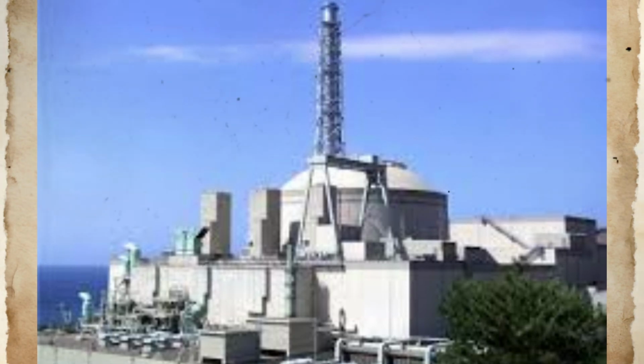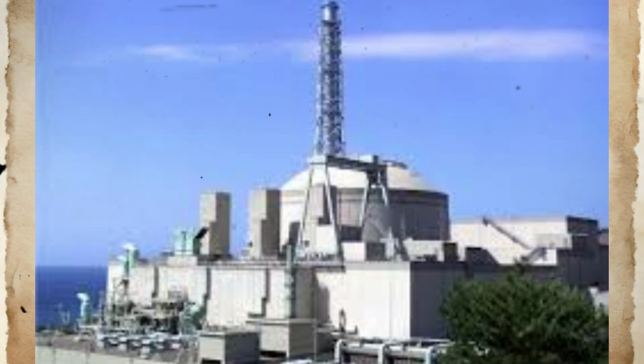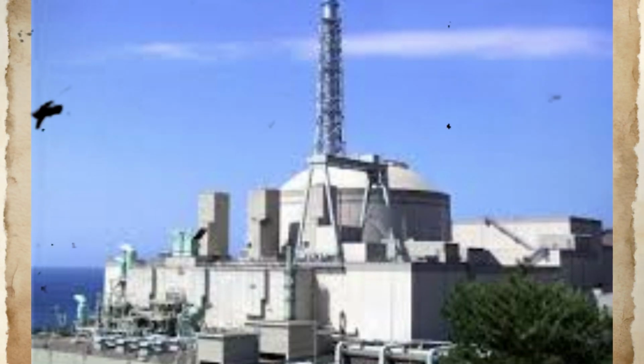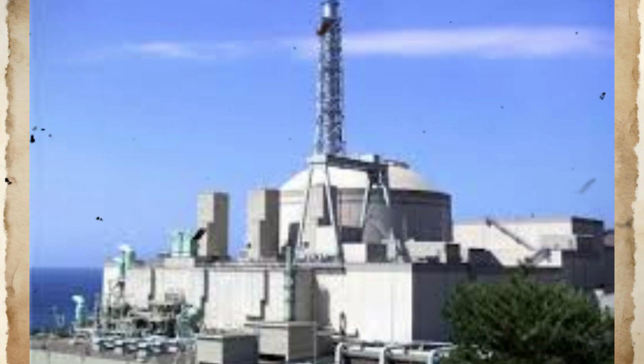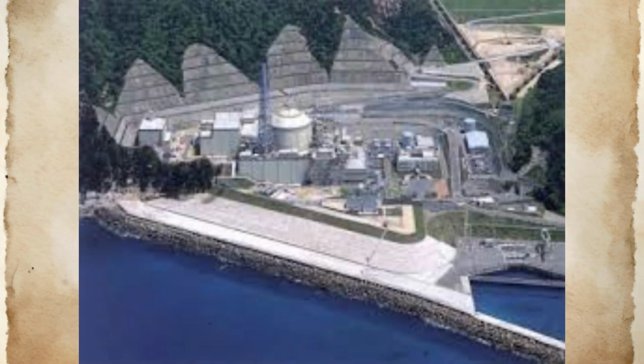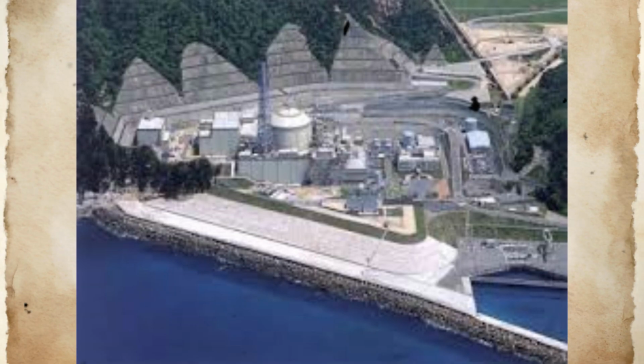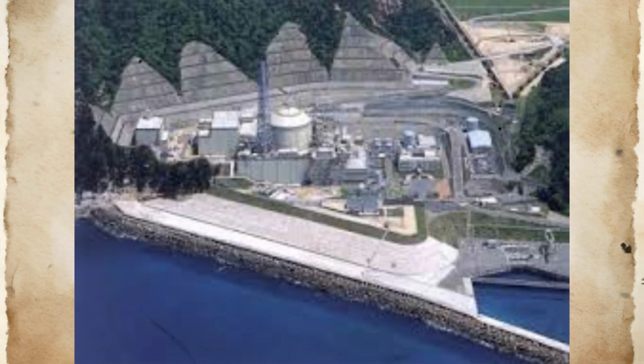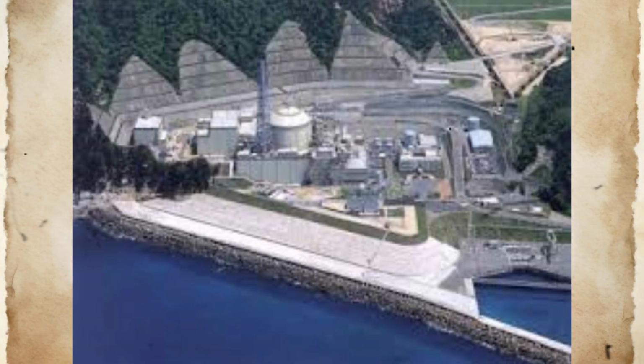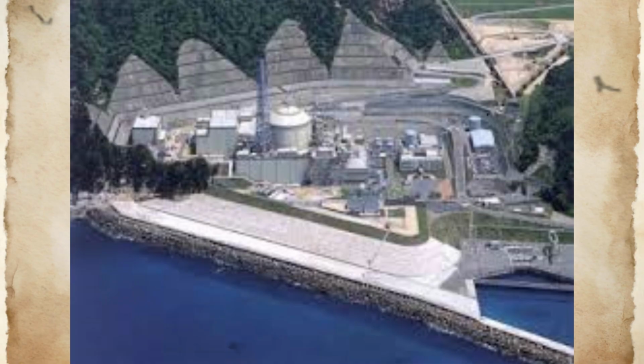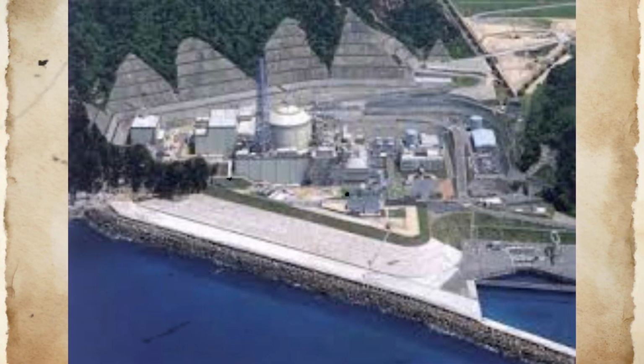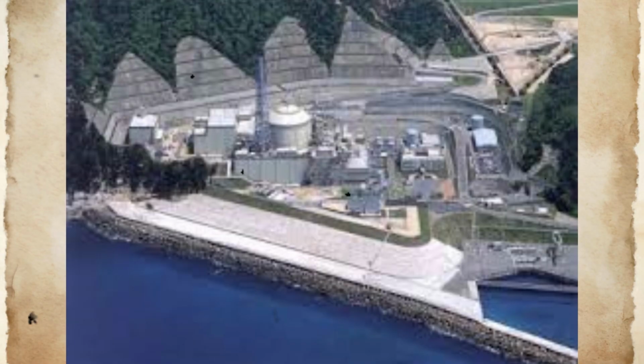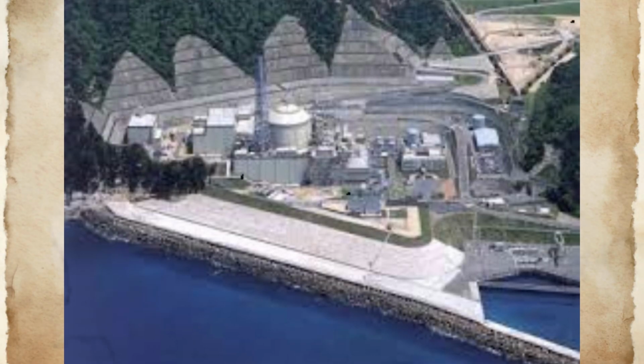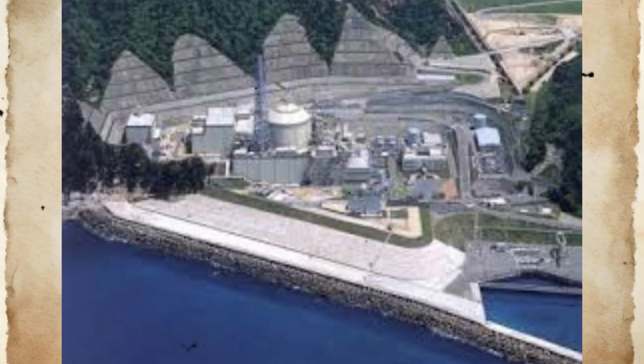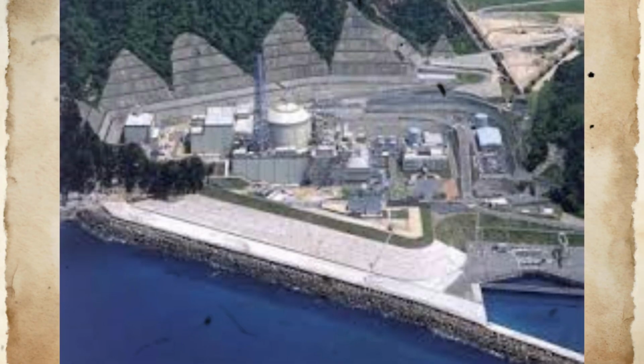The leak detection systems installed in the SHTS piping rooms were designed to identify the presence of sodium in areas where sodium should not exist under normal operating conditions. Detection was accomplished through conductivity measurements that could identify the highly conductive sodium compounds formed when escaped sodium reacted with atmospheric moisture. Leak detection system response confirmed sodium presence, but provided no quantitative information about leak rates or accumulated quantities. The systems were designed as binary indicators, sodium detected or not detected, rather than as measurement devices capable of characterizing leak severity or progression trends.